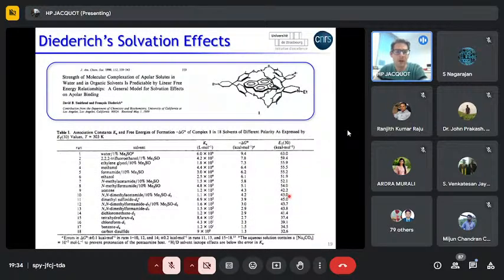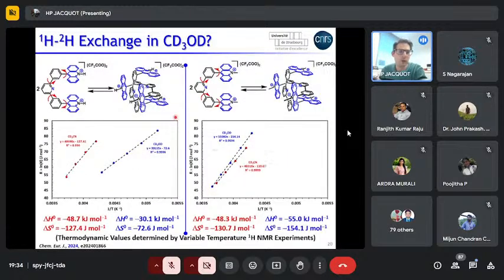And we looked at this paper called A General Model for Solvation Effects on Apolar Binding, which was written by François Diederich. And what it showed is that for pi-pi stacking interactions between aromatic moieties, we have an increase of the binding constant, or decrease of the delta G value, as you increase the polarity of the solvent. So what happens in our system? That was the question. So to understand, we compared the NH tweezer with the N-methyl tweezer. And actually what we do see is that for the N-methyl, we have an inversion of this tendency.